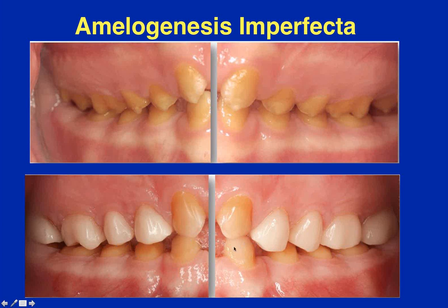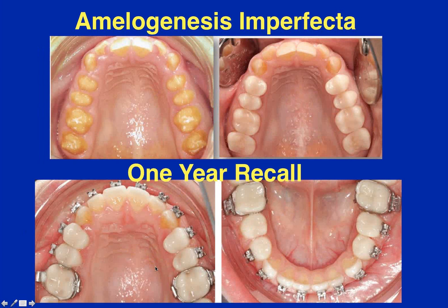From this perspective, even though we might not think the aesthetics are very good, the patient was ecstatic in how they looked versus what she was walking around with for most of her life. They even stressed it more by putting brackets on top of it. This was at 1 year recall. It's about 2 years now, and according to Dr. Preissner, they're still going well. At 0.3 millimeters, your ceramic would have cracked, and your composite resin most likely would have been worn through at this stage. So this is a really challenging case for this material that's survived so far very well.